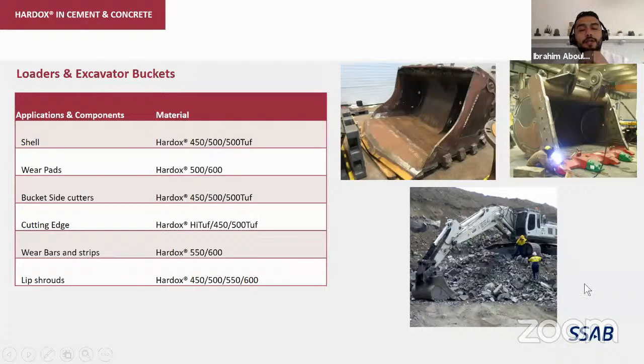Going to the bucket side cutters, which are on the side, usually we also recommend again 450, 500, and 500 tuff. I would personally recommend the 500 tuff, and the reason is the side cutters are not only facing impact from breaking the rocks or hitting into the rocks, and wear due to carrying the rocks and so on, but there is one hidden use. The side cutters more or less work as a structural component because they hold the shell together with the cutting edge. So they have also a structural use. For that, the 500 tuff would be an optimum solution.